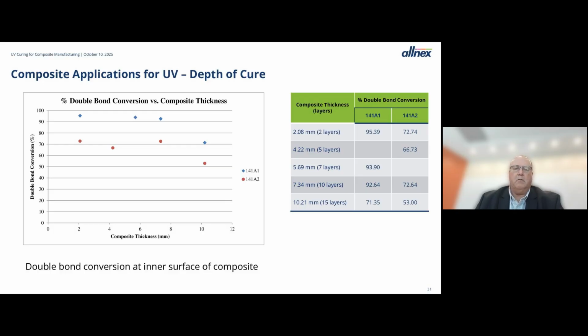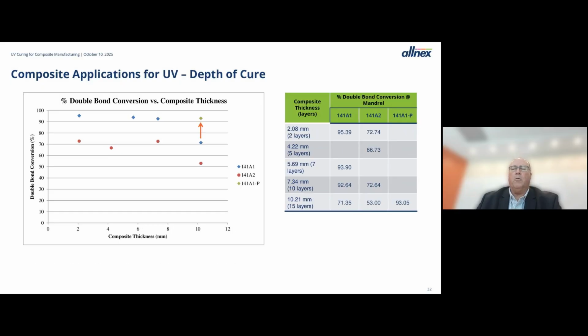There are solutions. One way to deal with that is if you put a little bit of peroxide into your system, the heat of reaction of the UV cure is sufficient to kick the peroxide cure off, and that way your composite will continue to cure even at very thick depths. So you can see here, the blue diamond or the red circles indicate the properties falling off around 10 millimeters for just a straight UV cure. But if we add a little bit of peroxide, then we're back up in that 90+% conversion, and the physical properties are similar to thinner materials.